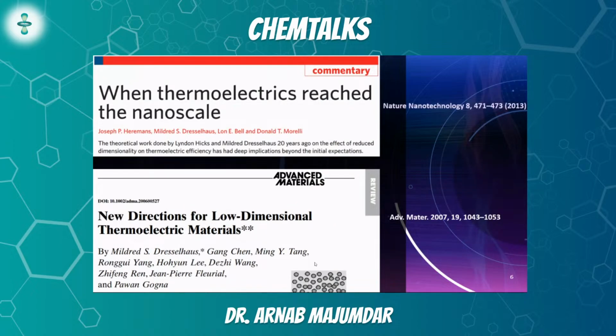Right. So the story goes, in the early 90s, Mildred Dresselhaus was approached by the US Navy as well as the French Navy to come up with a method to improve the thermoelectric performance of materials. What she proposed was that if we decrease the physical dimension of a system, then the thermal conductivity will probably decrease, as a result of which the thermoelectric figure of merit will probably increase.